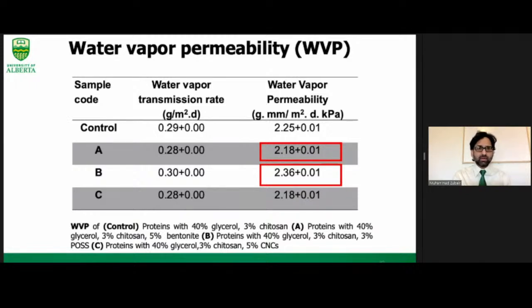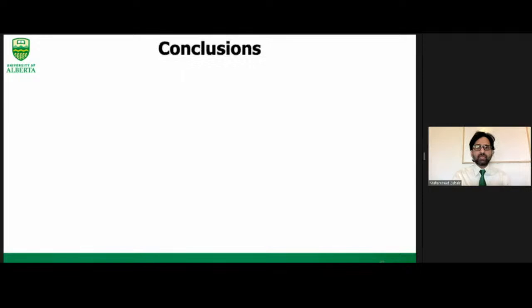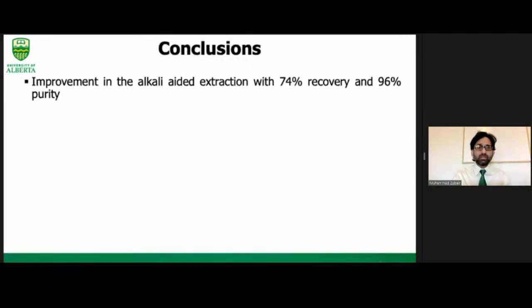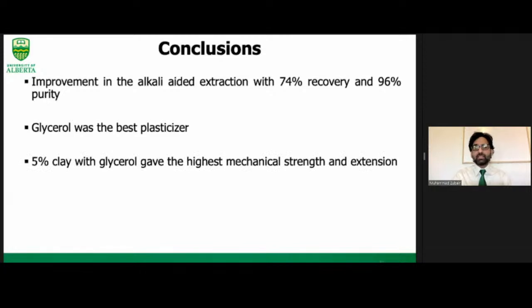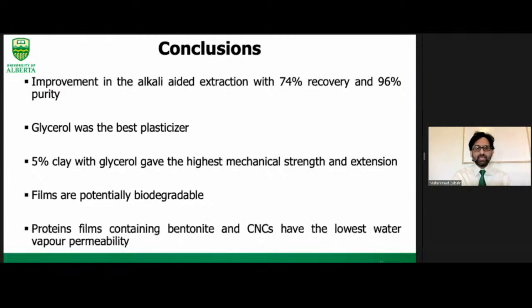From all these results, we concluded that the alkali-aided extraction is a good method to recover the proteins from the spent hen. And among all plasticizers that we screened out, glycerol shows the best results. And 5% clay, that is bentonite, shows the highest mechanical strength. And these films are potentially biodegradable, while the films containing cellulose nanocrystals have the lowest water vapor permeability.